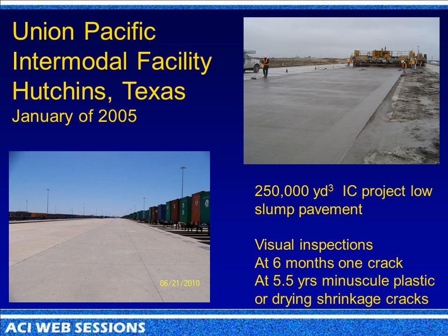Here's probably the largest project. This is also done in Texas, in Hutchins, Texas, 250,000 yards. And at 6 months, I think they might have been drinking or smoking something. They only found 1 crack in this whole thing. But anyway, they went out and looked, and they looked hard. But they came back 5.5 years later, and they did an extensive review. They had like 5 or 6 people running this whole job, looking for hours for cracks. And what they came out with was the plastic and drying shrinkage cracks were minuscule. I thought that was pretty impressive.